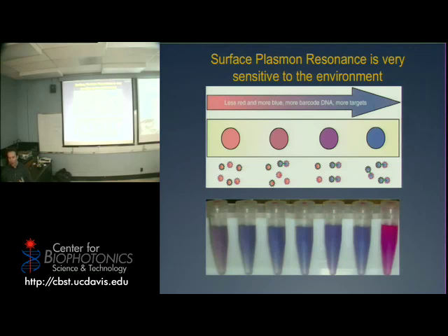Size. It's the size. So why do you think there is such a difference between the 5 and the 20 nanometers? Exactly, it's the surface area. These objects are really tiny. Especially the 5 nanometers, we're talking about maybe less than 1,000 atoms. So the number of atoms on the surface compared to the actual volume is humongous. And this surface to volume ratio obviously decreases as the particle goes up. So the 5 nanometer particle has a much more intense electrostatic field, because you have a charge that gets confined into a smaller and smaller volume.